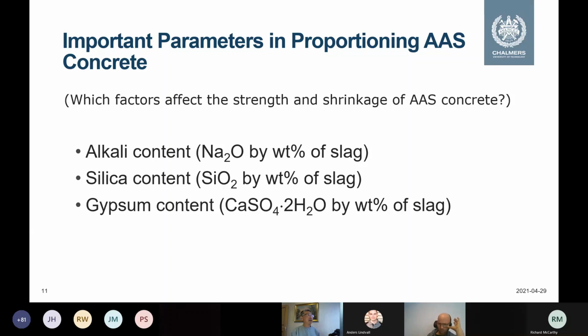These factors include alkali content, that is basically sodium hydroxide content, and then silica content. We know that sodium oxide content basically tries to increase the solubility of silicate. In our slag and also cement, we have a lot of silicate, silicon oxide, but the solubility of silicon oxide is very low, so we need the alkali to dissolve it. Because this dissolution process is very slow, we need to increase the early strength. In that case, we need to add silica content directly from water glass, so that is at the molecular level. This is why we use water glass.